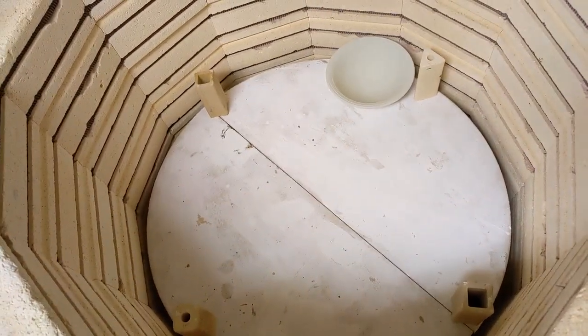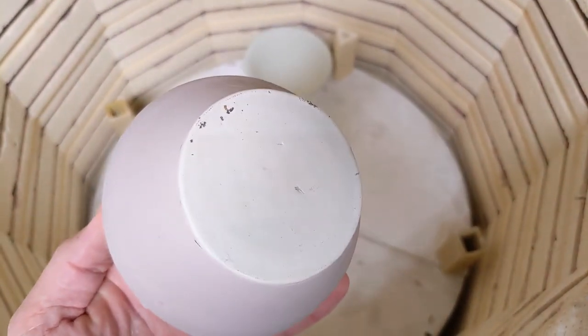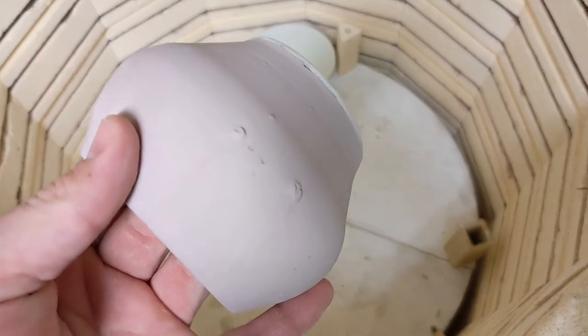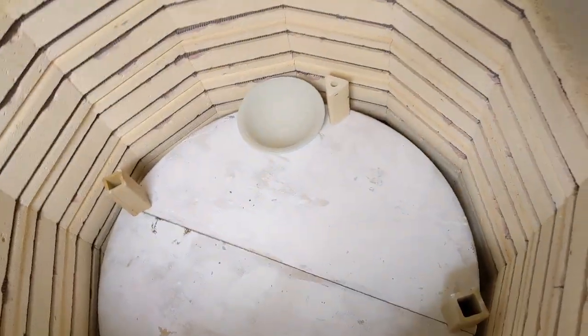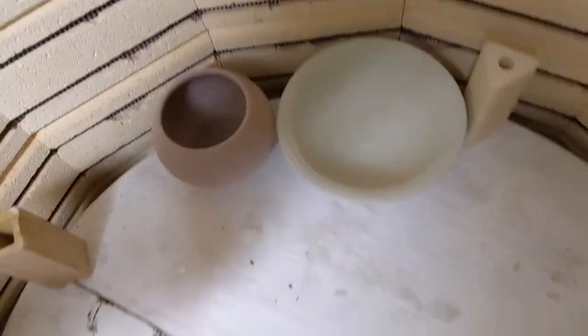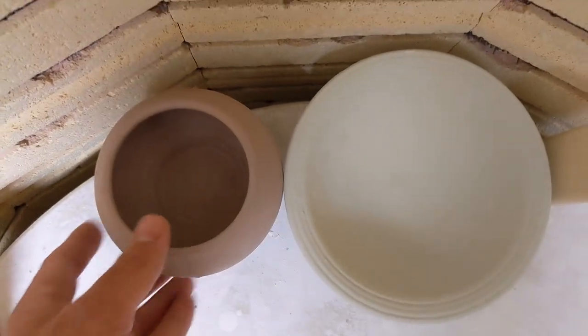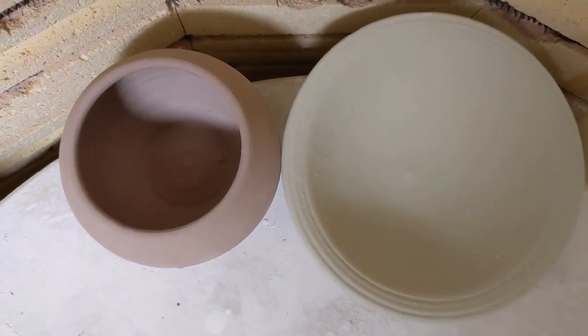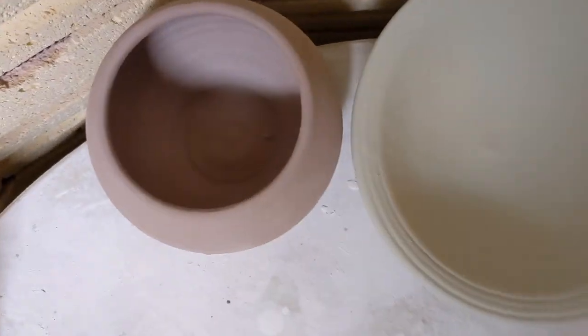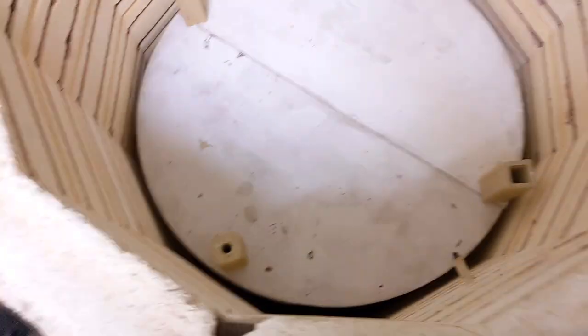Here we are in the kiln room, ready to load our piece. We've checked it off so I can give you the okay that the glaze is cleaned off, you've got it waxed back appropriately, and there are no glaze chunks missing. When you put it in the kiln, you're going to make sure not to leave very much space between the piece next to it. With a glaze firing, we want to get our pieces as close together as possible without touching them. If the pieces are touching, sometimes that will result in the two being fused together for good — we don't want to ruin somebody else's work. A credit card thickness in between them is plenty, and we want to try to get as many pieces on the shelf as we can.